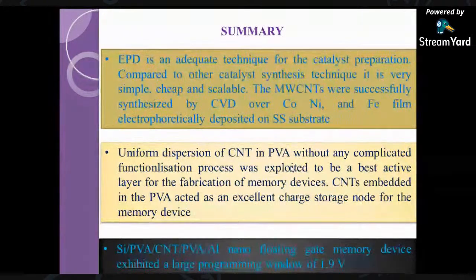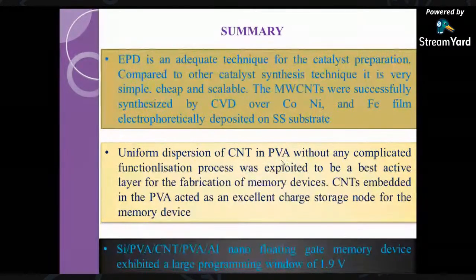Coming to the summary, I will wind up here with the summary of the findings that we have seen. EPD, the electrophoretic deposition technique, is considered to be a simple tool to create multiple carbon nanotubes using various layers and various catalysts like cobalt, nickel, and iron over stainless steel. And then we have carbon nanotubes dispersed with PVA, and we can take PVA as a good candidate for dispersion of carbon nanotubes for more applications in memory devices.